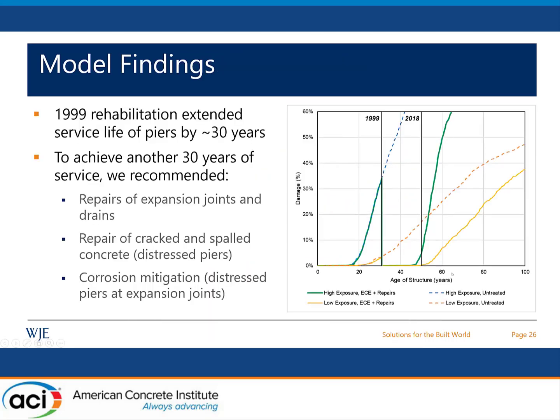So based on our model findings, we were able to estimate that the rehabilitation, which included the ECE and joint repairs, extended the service life by about 30 years. However, we also found that moving forward in time, there was a high likelihood that we would exceed damage fractions of 20 or even 30% on these piers, and that they wouldn't necessarily reach the intended additional 30 years of service life.